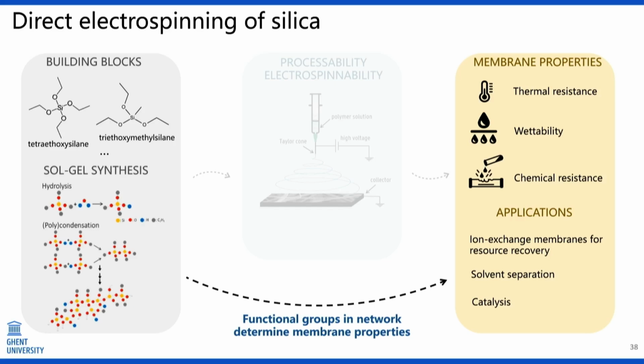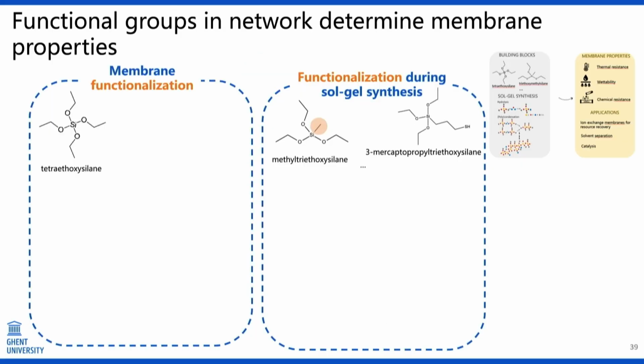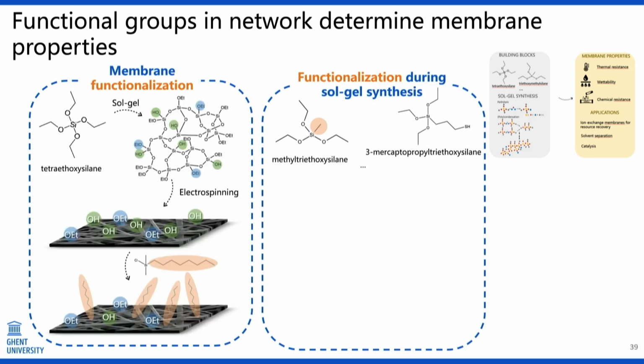So that brings us to the membrane properties, and for many of these applications we indeed need additional functional groups. Now, silica can be easily functionalized. It can be done both ways if you start from TEOS: you can first spin the membrane and then functionalize the membrane, or you can introduce different precursors, already introducing the functionalities during the synthesis. If you spin a TEOS membrane, then there are still some free ethoxy and hydroxyl groups present, which can be used for further modification and bringing in, for instance, hydrophobic groups.